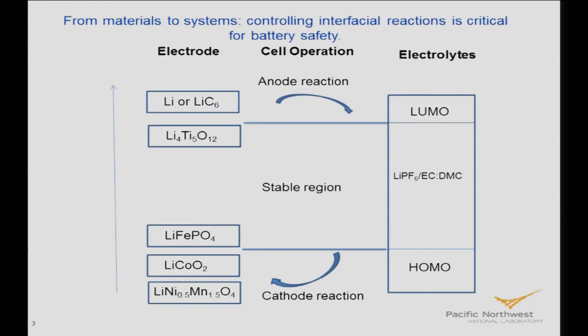Now, if we use graphite, or even lithium in the future, you are on the high side. That means intrinsically you have charge transfer from the electrode material to the electrolyte. That really causes the so-called dendrite formation and fire, those kinds of things. You can have the same kind of issue in the cathode material.